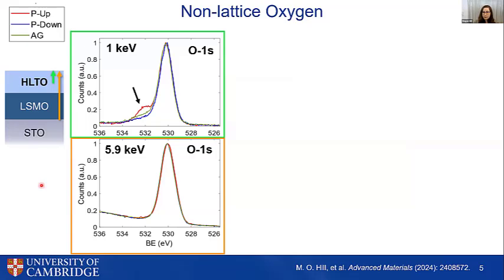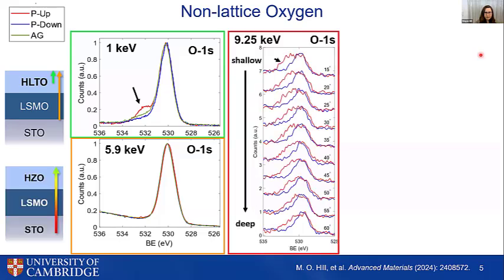Now, this peak is potentially controversial because it's often referred to as oxygen vacancies, but we refer to it as non-lattice oxygen because it's simply an oxygen species that isn't singularly bound to the hafnia or lanthanum or tantalum atoms. So it could be from a number of things, including surface hydroxyl or hydroxide formation, or bulk oxygen interstitials, or bulk hydrides. And while it's not direct evidence of changes in oxygen vacancy, it can be a secondary effect of vacancy reorganization. So it's quite complex, but we'll just call it non-lattice oxygen.